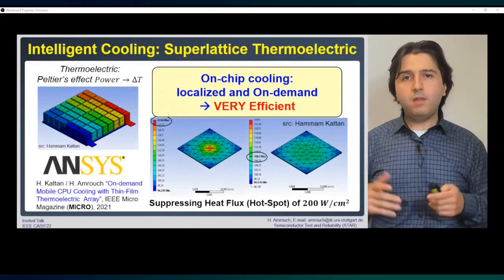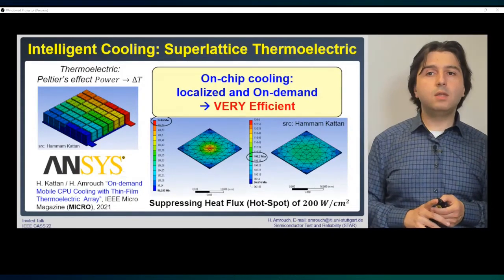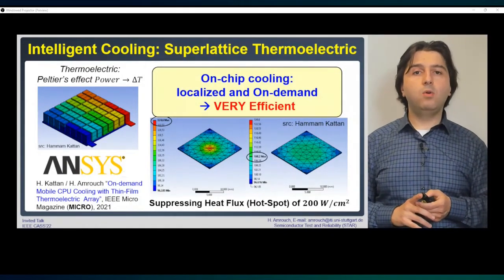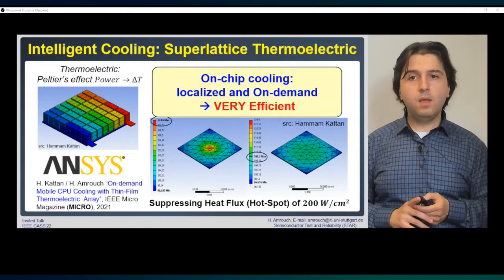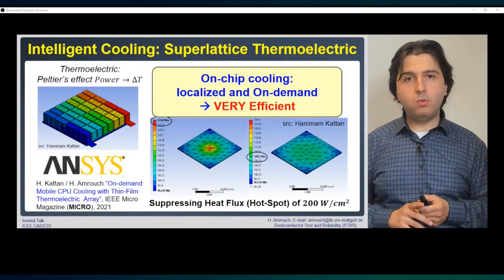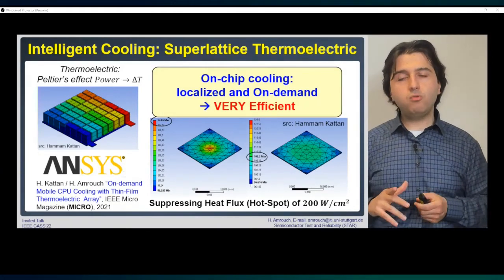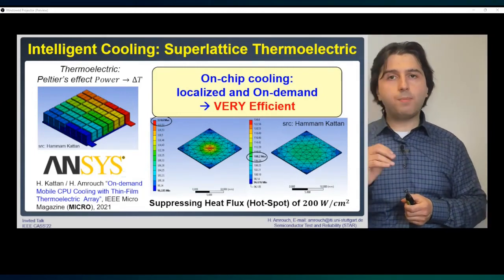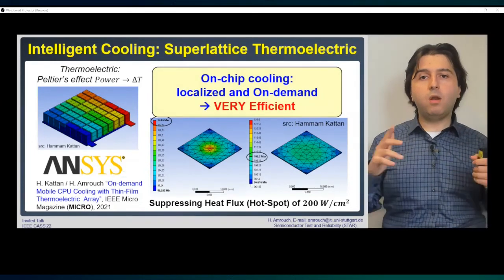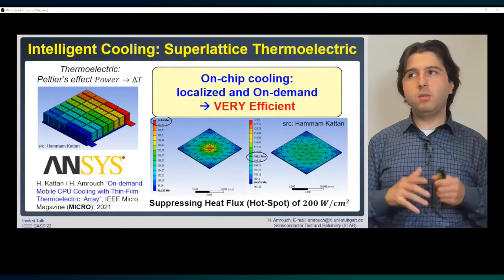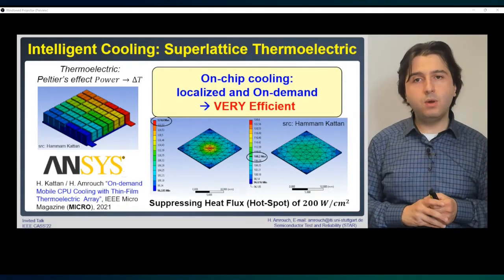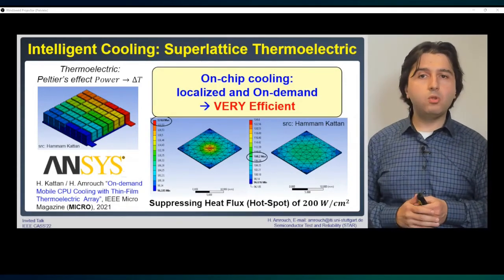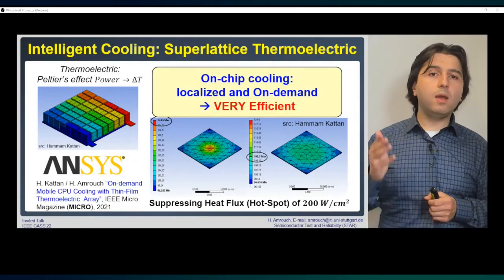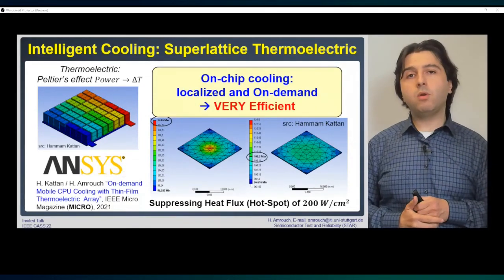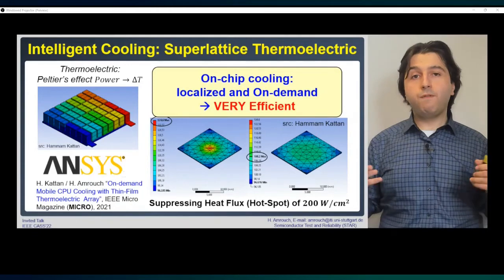We have done extensive work on studying the impact of thermoelectric devices using complex multiphysics simulations from ANSYS, and it turns out you are able to really suppress a hotspot coming from around 200 watt per square centimeter, which is a very large power density as we know, leading in this example to around 125 degrees. We are able to suppress it all the way down to around 108 degrees, which is very, very promising.